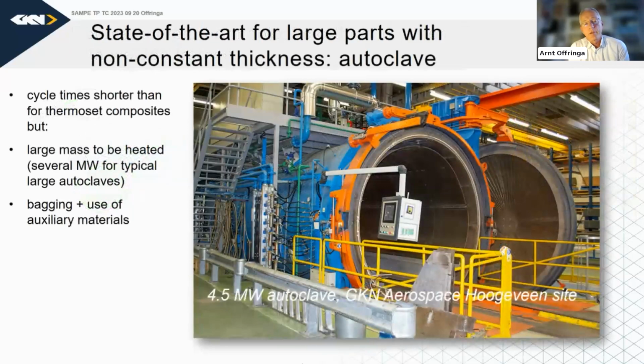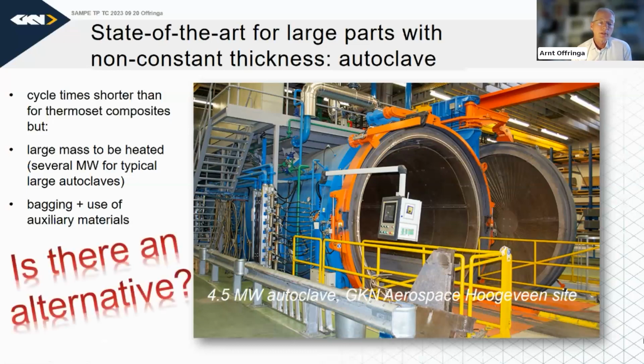So what is the state of the art? For large parts, really large parts with good quality, mostly we have to go into an autoclave. And the cycle times are shorter than for thermosets, but we do have a huge mass of steel and tooling to heat up each time. This autoclave here, which is a 3.5 meter diameter, is about 4.5 megawatts. So that's a fairly powerful autoclave. And we have a lot of bagging to do each time. We bag our products with flexible foils that most often we cannot reuse. So the question is, can we find an alternative to this?